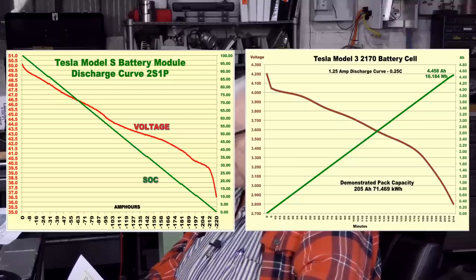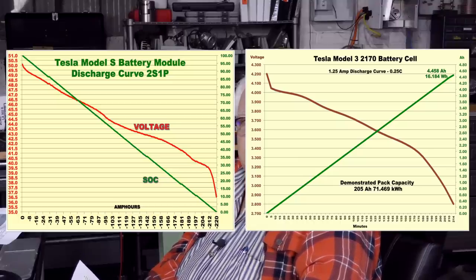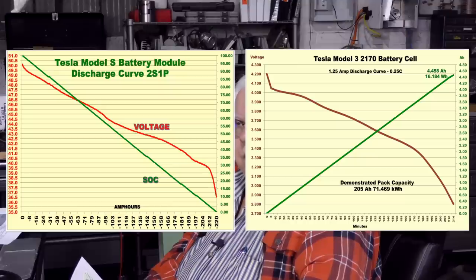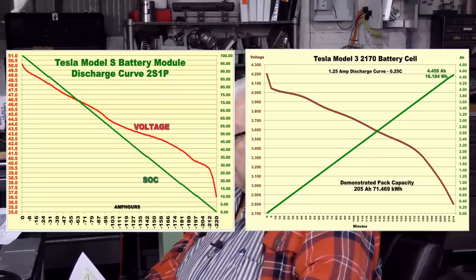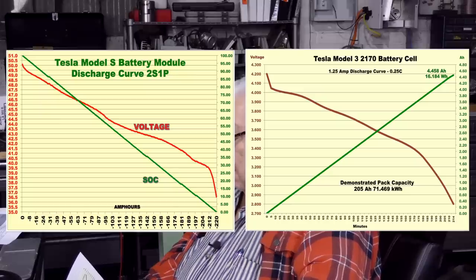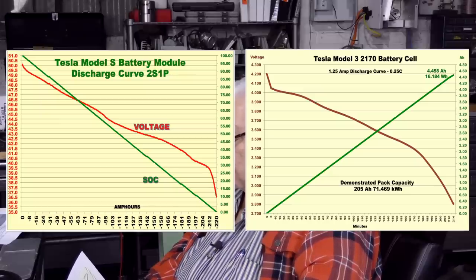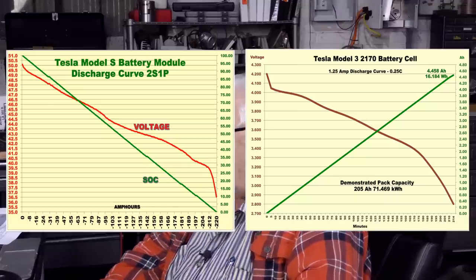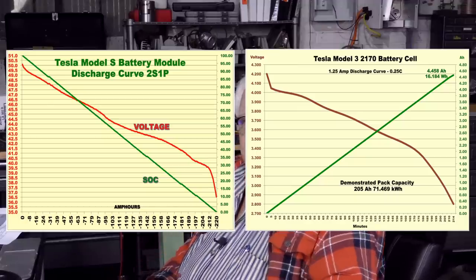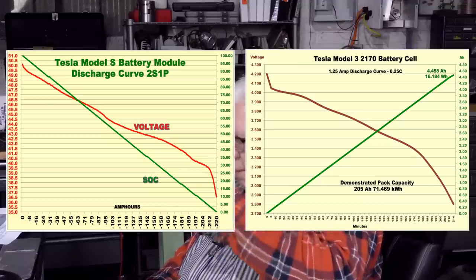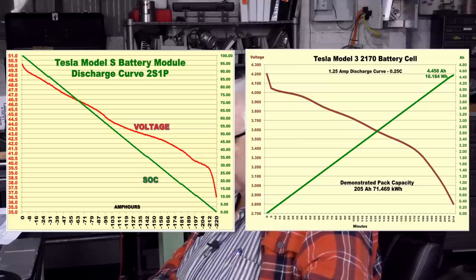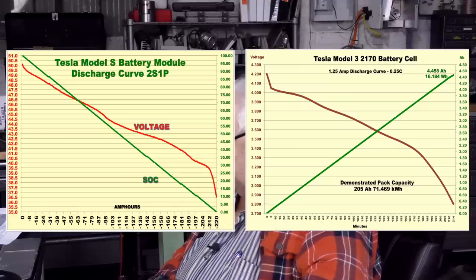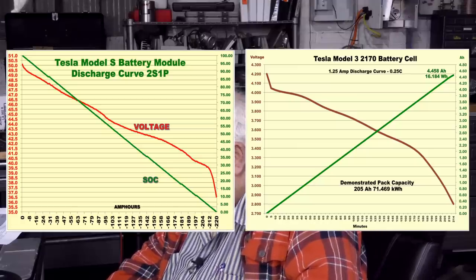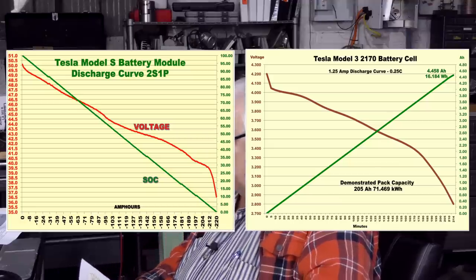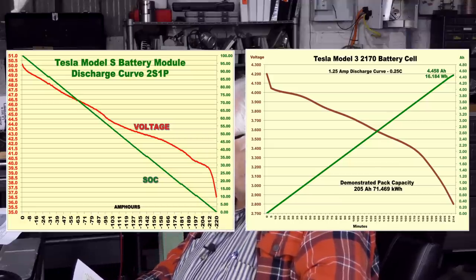I would say some of the hook on the end of the going vertical on the Model S is a little flattened out for the Model 3. The jump from 4.2 down to about 4 volts is mostly surface charge, but it is pretty vertical at that point. And that's the discharge curve for the Model 3 battery.